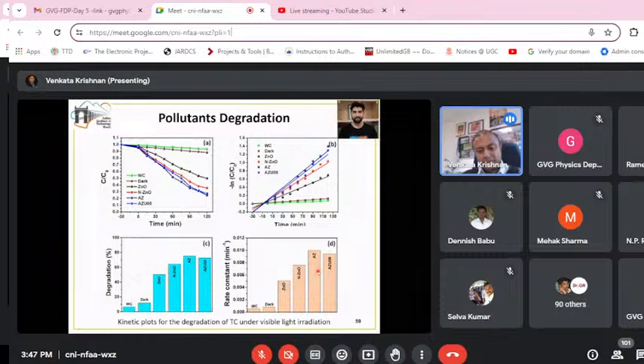Then we did the same experiment, but under visible light irradiation. Here the AZ sample gave the best photocatalytic activity, and the main activity is due to the gold nanoparticles and its surface plasmon resonance.